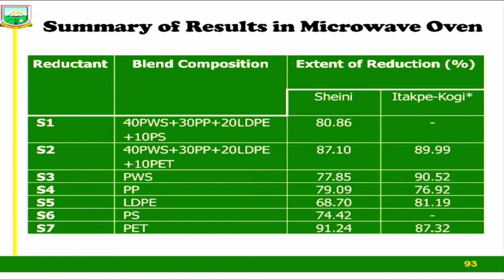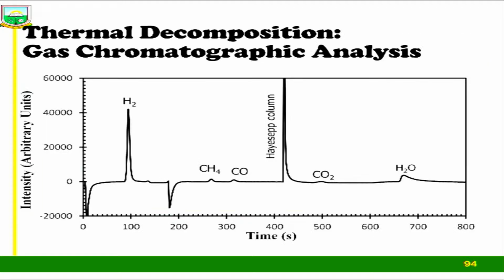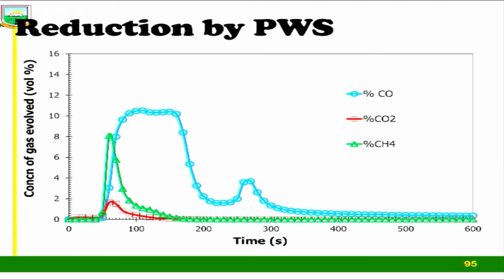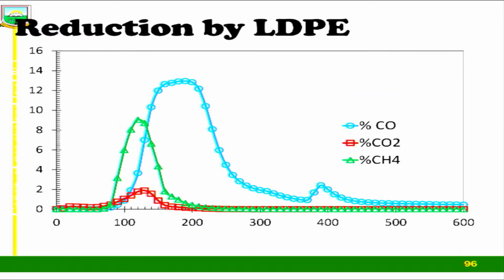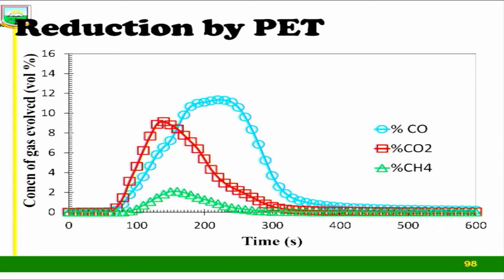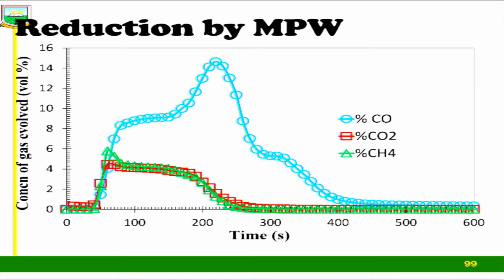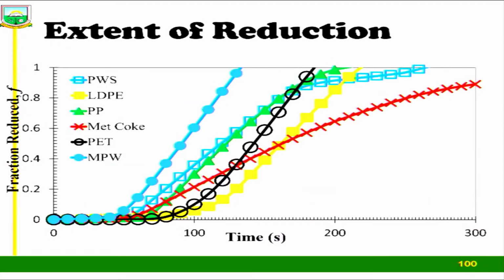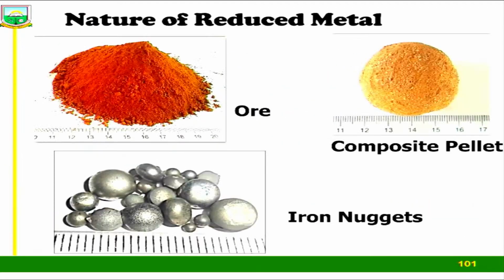Reduction degree up to about 91.24% when we use PET as the reducing agent. Went through this, and then these are the reduction concentration of gases that were produced in each case. And a bit of the metal that we produce.